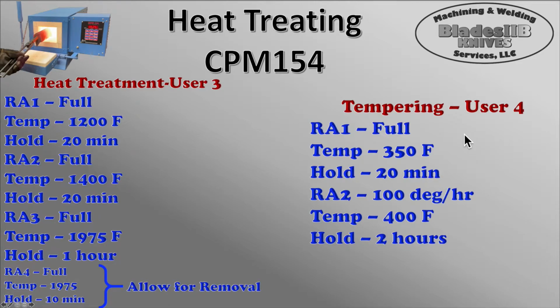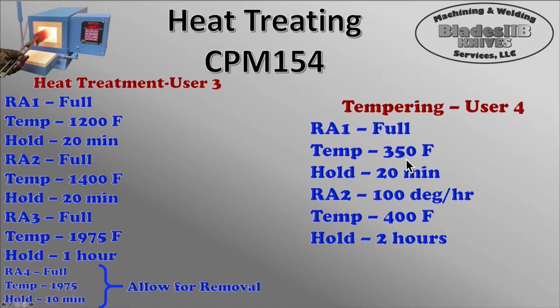For tempering, this one is going to be very similar to what we did for the 440C. We're just going 50 degrees higher overall. So we're going to ramp full speed up to 350. Going to let that sit for 20 minutes to let the kiln normalize a little bit this time. So when I'm ramping at full speed, it's probably going to actually heat up to about 360, maybe a little above 360. And we're going to hold it there for 20 minutes. Gives our kiln a chance to get everything up to temperature, stabilize.